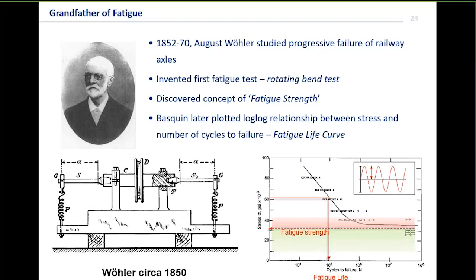Now, Wöhler was testing mild steel under constant amplitude sinusoidal load, and it is true that you find that there is a fatigue strength threshold for mild steel under constant amplitude loading. But more generally, for most materials, that's not true. If we look at an aluminium alloy, for instance, we see a very definite change at that transition, but it's certainly not an infinite life. And even steel, under variable amplitude loading, has a gradient to that line. It's not infinite life, but we'll come to that later.